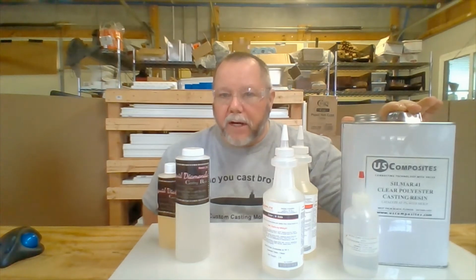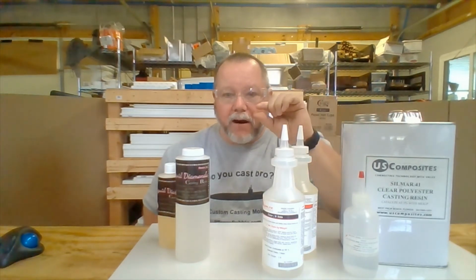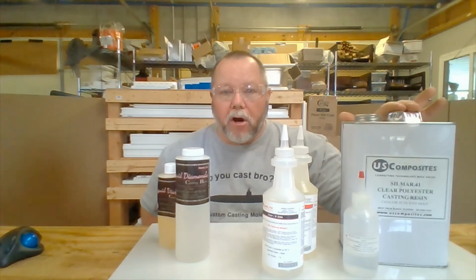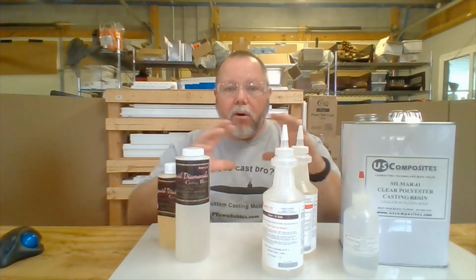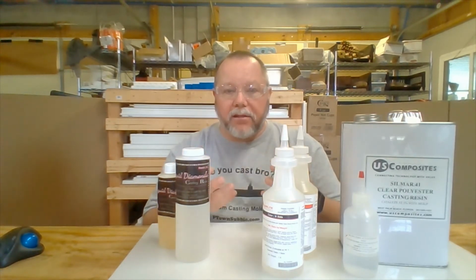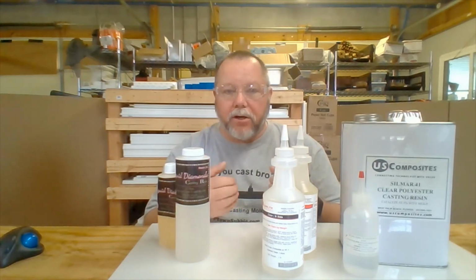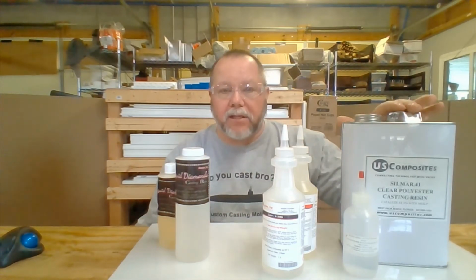If you look at the instructions, they will tell you either 10 or 20 drops per ounce, but they're thinking you're casting a very thin sheet, not a really large, deep pen blank or larger casting. So 3 to 4 drops per ounce, and the larger your block that you're casting, the less MEKP you need to add, because the more material you have, the more heat that's developed. The more heat that's developed, the faster it cures. The faster it cures, it creates heat. So you can see it's a chain reaction type process.